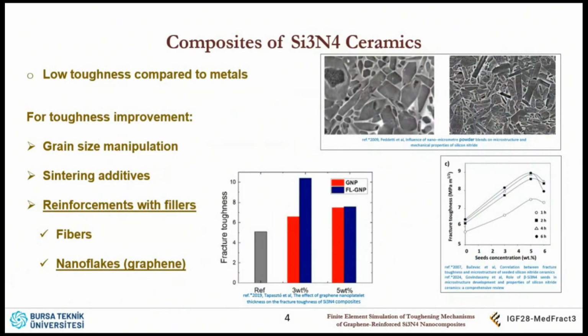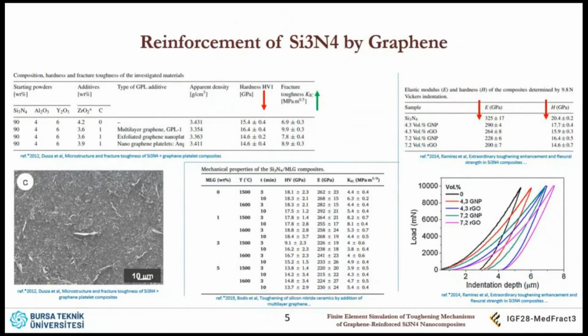So if this material is so good, why are composites of this ceramic needed? Researchers are always after better materials, so they want tougher ceramics because ceramics almost always have less toughness than metals. So in order to improve the toughness, researchers manipulate grain sizes. They add some sintering additives, or they add some fillers like fibers or nanoplatelets. When they do this, they get some improvements in fracture toughness. However, other mechanical properties may degrade, such as Young's modulus and hardness, while the fracture toughness improves.